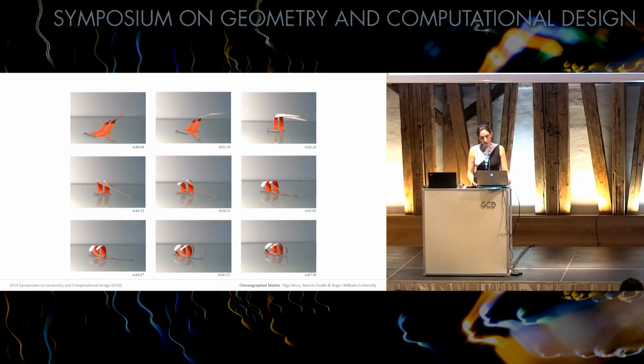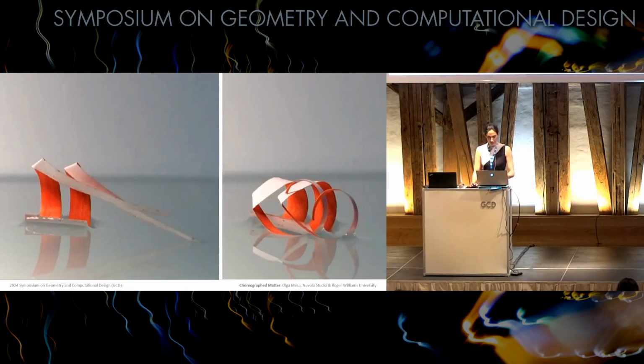The temperature of water changes the surface tension, which translated into either slowing down the actuation or accelerating it. I was playing with that to control certain actions of the origami constructions. In the images above, we see an out-of-plane fold that then anchors a leg of the design to then try to latch back onto it as it curls. Didn't quite work, but it almost did. Here's a closer look at it, trying to tie a knot.